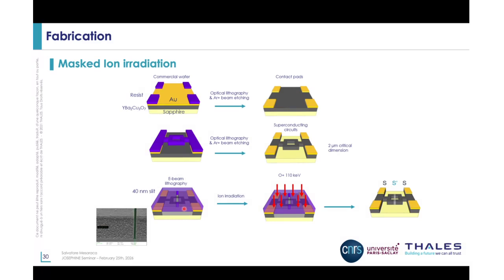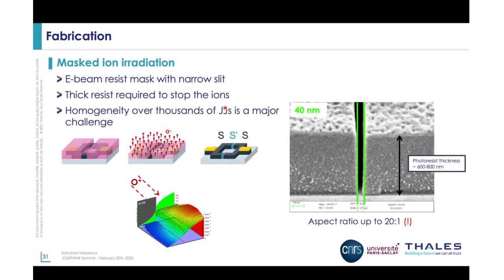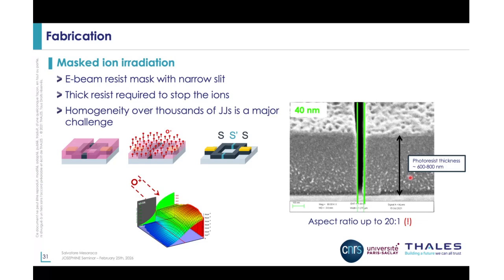As I said, this is the complicated part, especially the first part, which is the lithography itself. I know that this sounds a bit weird to say that 40 nanometers on E-beam is complicated to do because it's exactly what E-beams are used for. But usually this is done on resists which are thick only tens of nanometers. We have to do it on resists that are thick up to 800 nanometers. So that means that our aspect ratios go up to 20:1. So it's a very big task to be done with the E-beam lithography.